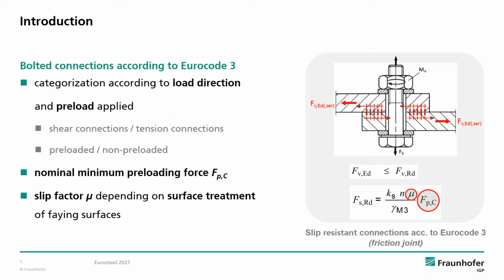For a better understanding, let's have a quick look at bolted connections according to Eurocode 3. Within the standard, bolted connections are categorized according to load direction and the level of preload applied. So there are shear and tension connections as well as preloaded and so-called non-preloaded connections. Slip-resistant connections are preloaded shear connections, which you might also know as friction connections or friction joints. For these connections to work properly, you have to apply a minimum preloading force, which depends on the size of your bolting assemblies. Also, you have to consider the slip factor, which depends on the surface treatment of your faying surfaces.